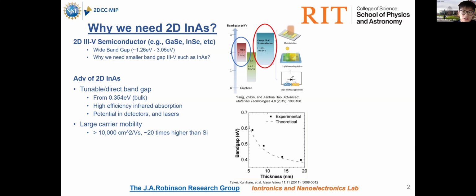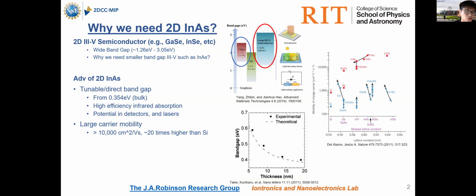Also, thin film indium arsenide has a thickness-dependent bandgap. So you can actually play with the thickness, and papers have demonstrated this in both theory and experimental data. Indium arsenide also has a large carrier mobility, beneficial for use in high efficiency transistors or nanoelectronic devices. It's almost 20 times higher than silicon.